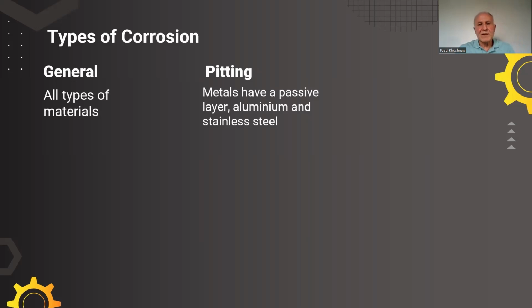With pitting, this usually happens when there is a passive layer. The layer cracks, and ions, for example chloride ions, attack the surface and go inside, making the pit larger inside, even if you don't see it on the surface. Mostly aluminum and stainless steel have this thin oxide passive layer on the surface, but some ions can attack the surface and make cracks or scratches, allowing other ions to go inside and cause corrosion inside the material.